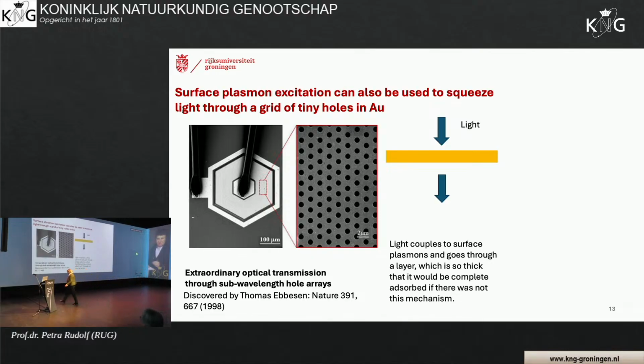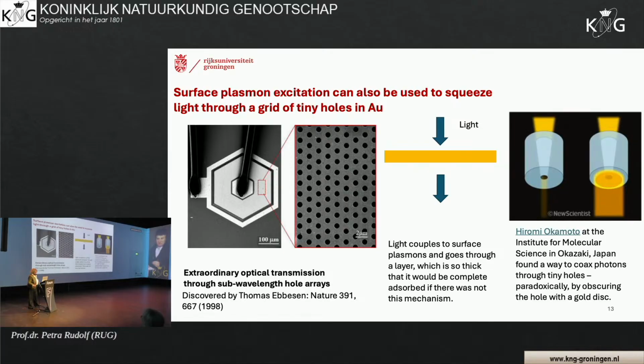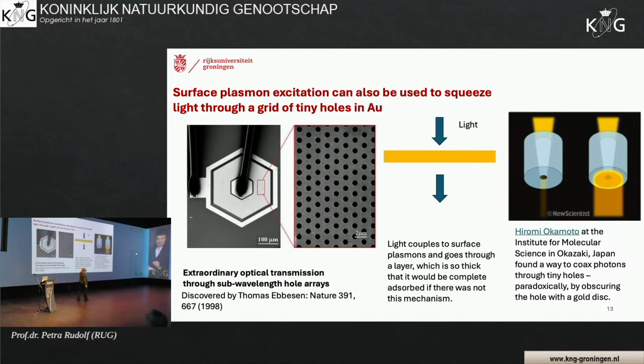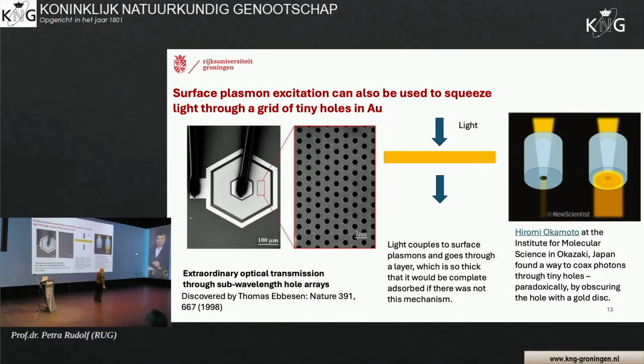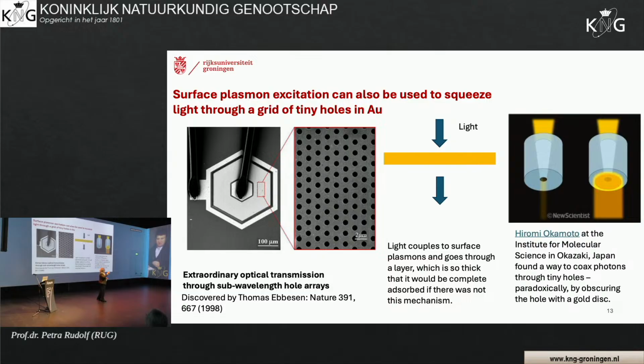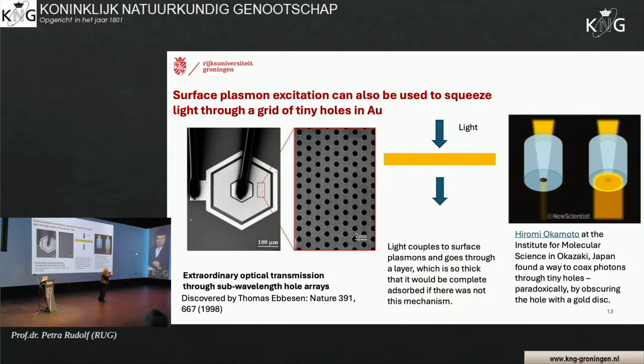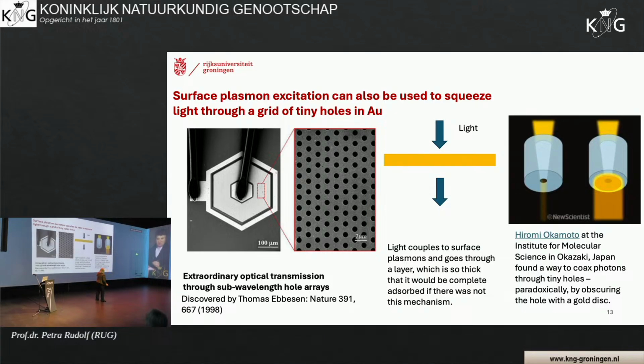And this can be used because it works also with very tiny objects. And this is used, for example, for optical fibers. Normally, when you have a very small hole in the optical fiber, the intensity which comes out here is not very big. But the Japanese research group found out that if they put here a tiny little gold disc of 100 micron just in front of the hole, not covering, not attached to the hole, but just so you can excite the surface plasmon, you get a lot more light out in this way. So these are all tricks which are related to the properties of gold when it is very small.